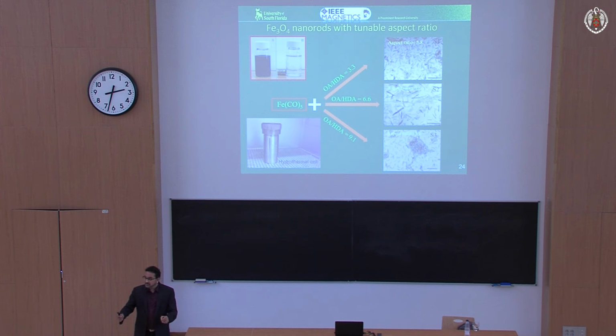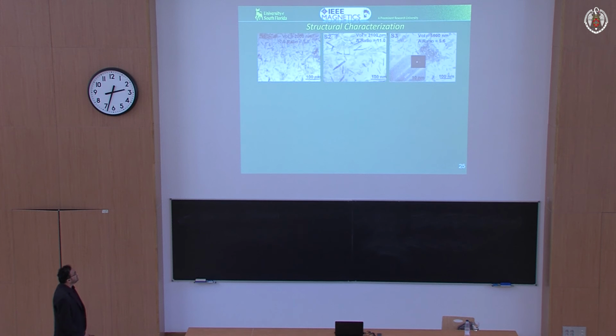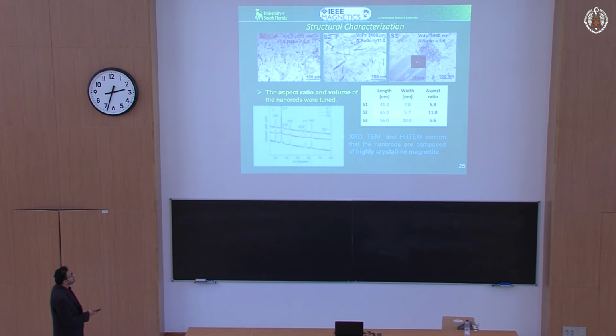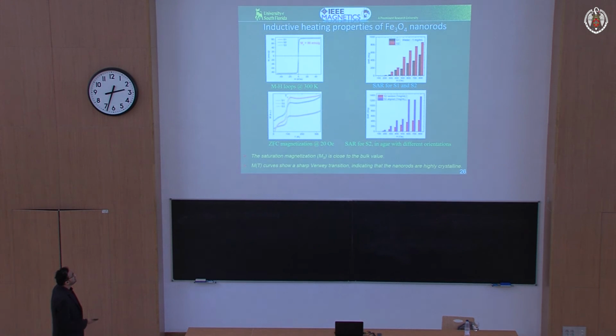One important thing about particles is that if you want to get the best SAR, you need to make the best particles. The particle quality has to be very high, which means you need to have very high single crystalline nature and also try to achieve the highest saturation magnetization possible in comparison to the bulk, okay? We did that, and we were able to achieve this in these nanorods. We did some studies on aspect ratio and found the best one and all that. But let me show you the results.